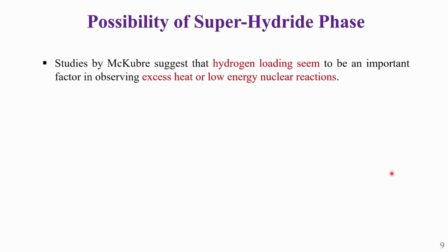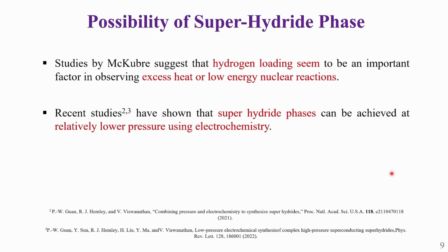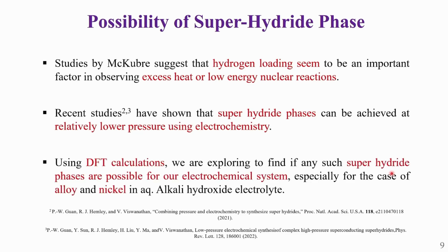Possibility of superhydride phase. As mentioned in the previous slide, studies by McKubre show that the amount of hydrogen loading in the sample is a key factor in determining the reproducibility of excess heat experiments. In the recent studies done by Vishwanathan and group, they have shown using what they call the pressure potential method that the formation of superhydride phases such as PdH10 are facilitated even at low pressure in an electrochemical system.